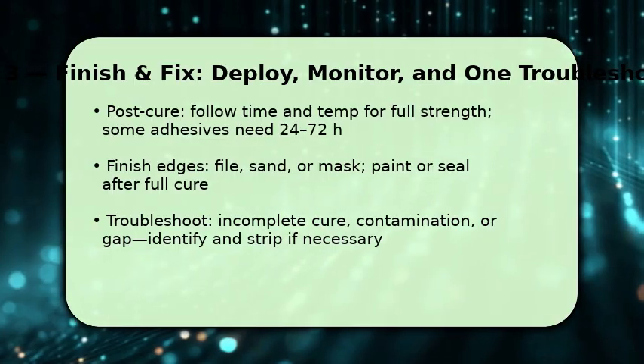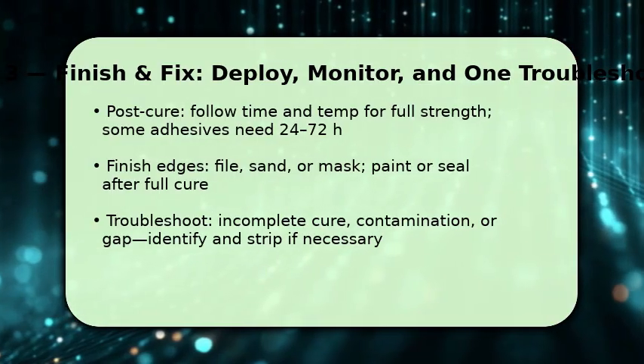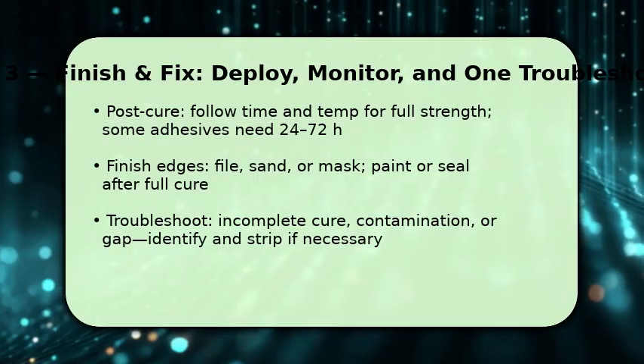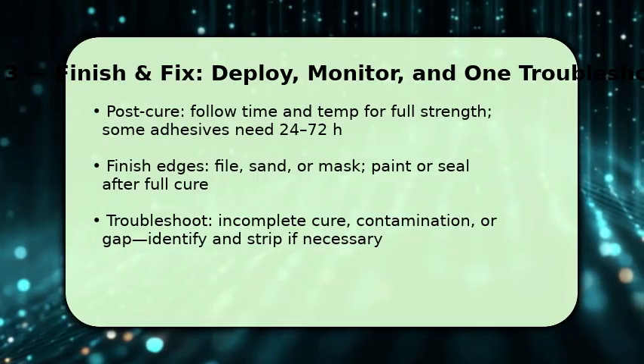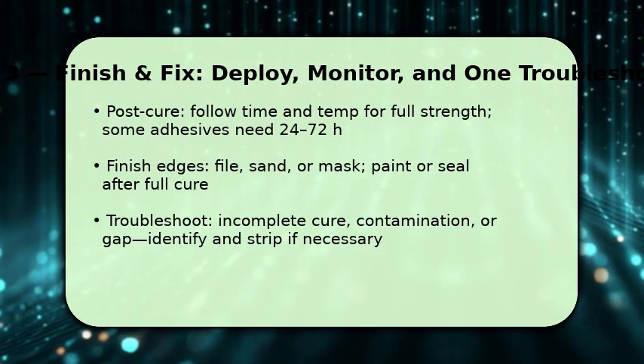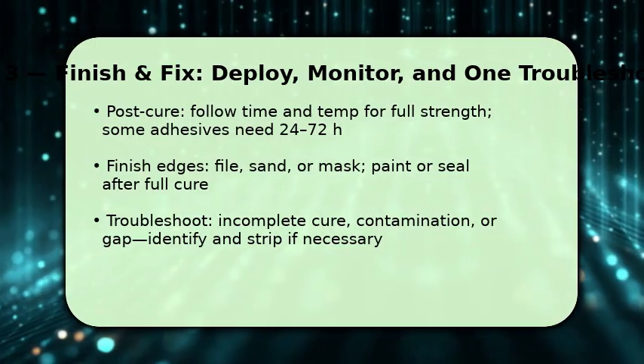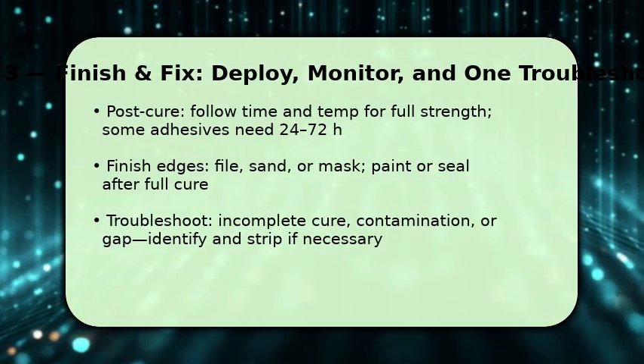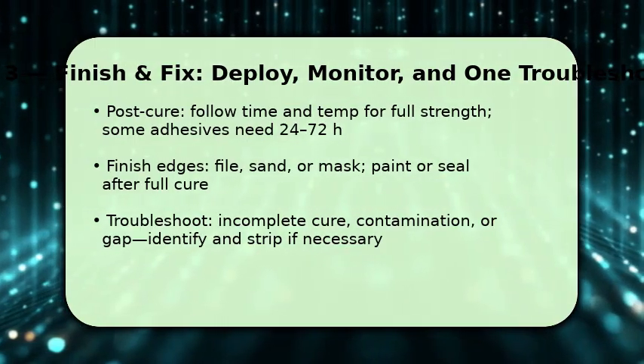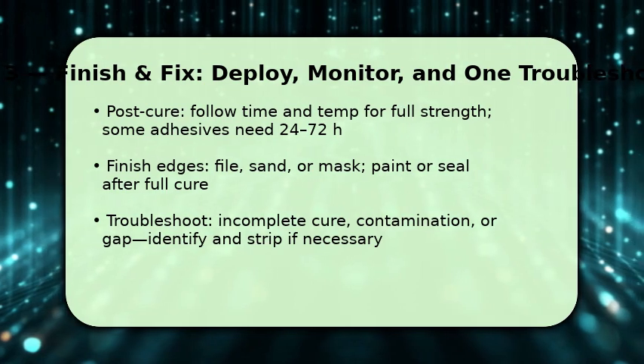To test, apply progressive load rather than a single shock. If failure occurs, check for contamination, incorrect mix ratio, or insufficient clamp pressure. These cause incomplete cure or weak joints. If contamination or major gaps exist, strip the adhesive, reprepare surfaces.